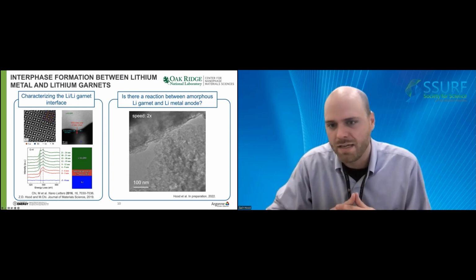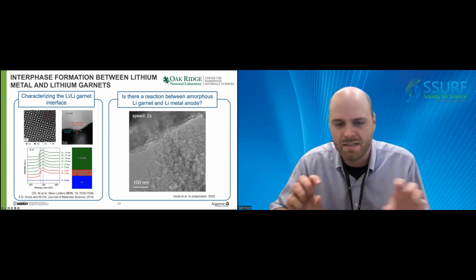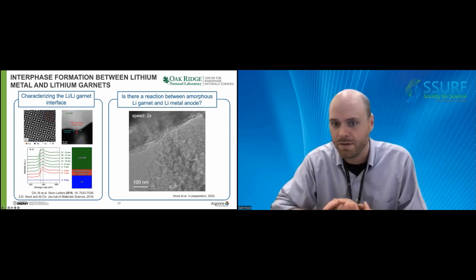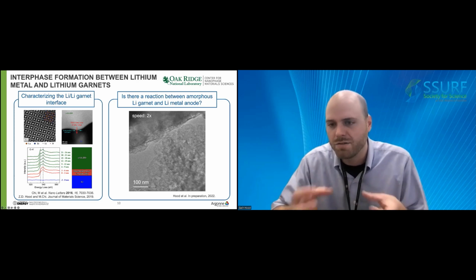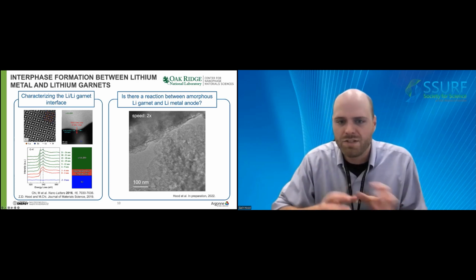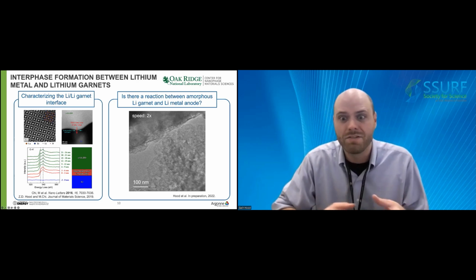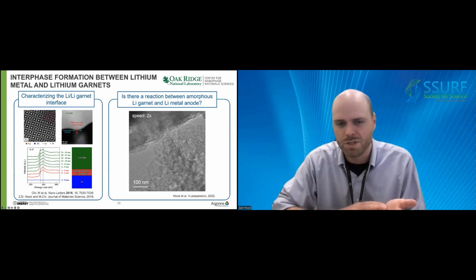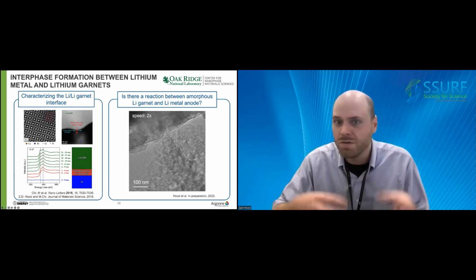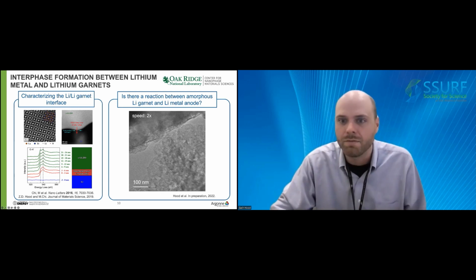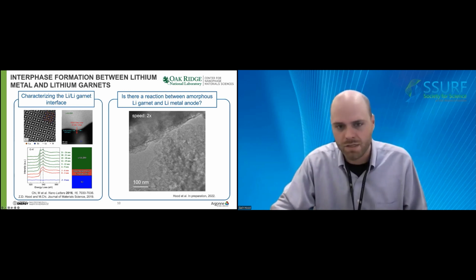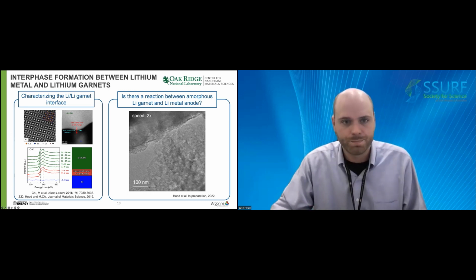And an EELS line scan across this interface shows a very tiny difference in the oxygen K edge of this inner layer, being confined to around 5 unit cells. And this change is correlated to a phase transition of the interface, which stabilizes that interface. So using these types of techniques, we really can reveal the stability of lithium metal with solid-state electrolytes, as well as the morphological changes in our materials.